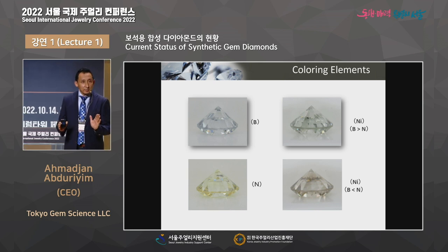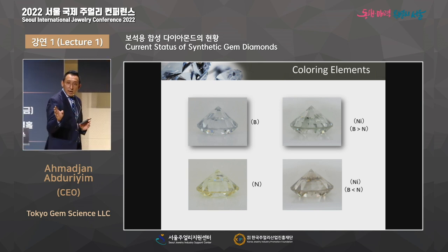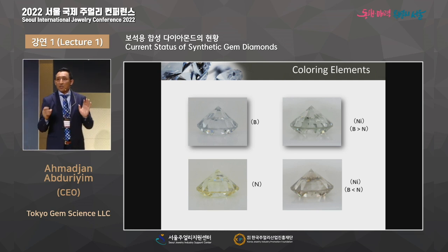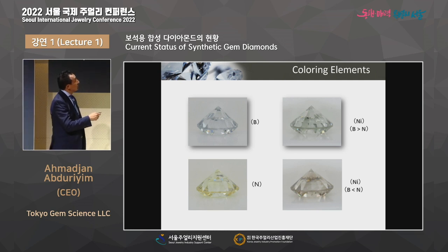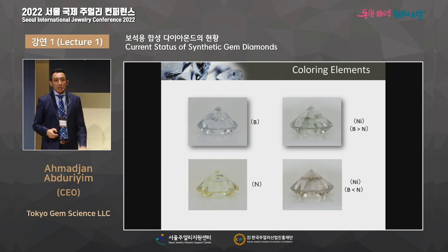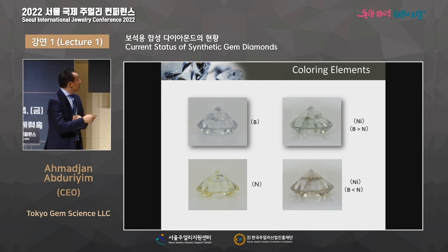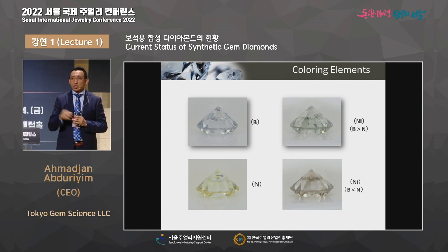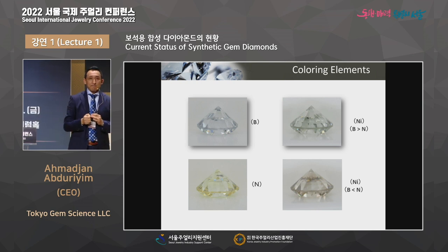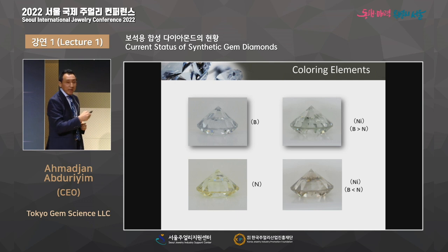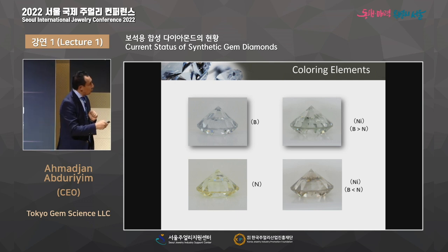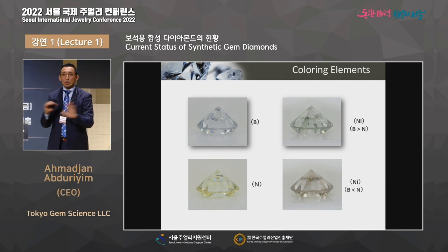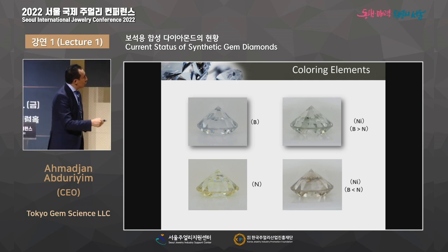Wait a minute, not really. They have colorless diamond, and they also have a slightly different color hue, like this. They have a small amount of boron to create a bluish color. This boron is not intentionally added. It's just from the metal flux, as an impurity. So they can create a slightly bluish color, and when you have nitrogen, of course, it always creates a yellow color. And these two have slightly greenish and brownish, all due to the nickel.